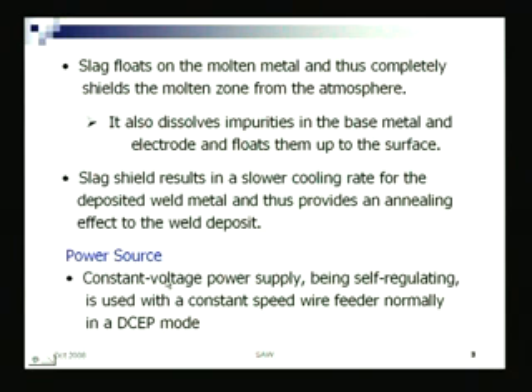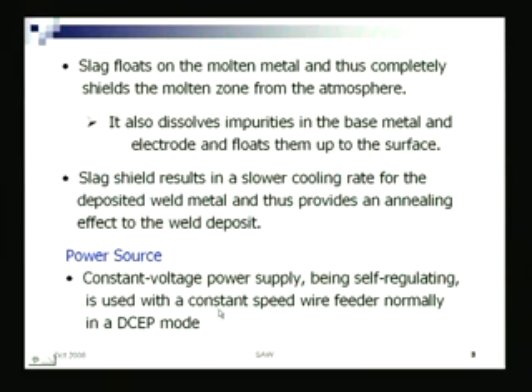What power source is used here? Generally a constant voltage power supply is used with electrode positive. Why constant voltage? Because it is a constant feeder mechanism, the electrode is fed continuously in an automated fashion, so I can keep the arc length constant. If that is so, then it is better to use constant voltage power supply with electrode positive mode.